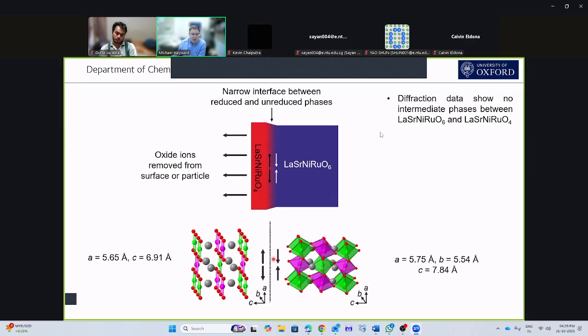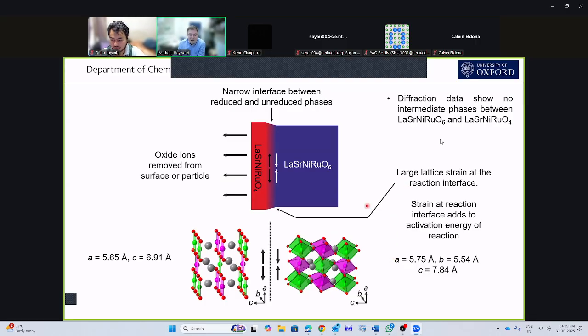And if we look at the unit cell sizes of the reduced and oxidized forms, we can see in the AB plane, compared to the A over here, there's a difference. So we're about 0.1 angstroms different in the lattice parameters, but that's 0.1 angstroms out of 5. So you can see that's about a 2% lattice strain, and that's a very high lattice strain. And in fact, this lattice strain at the interface adds significantly to the activation energy of the reaction.